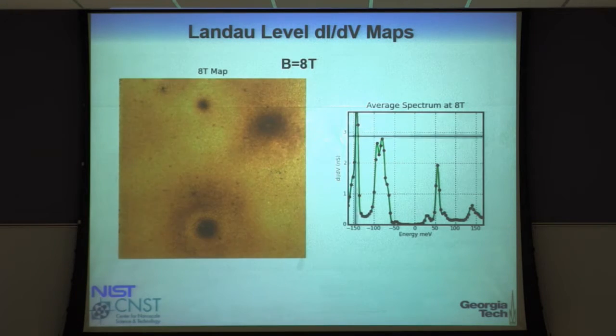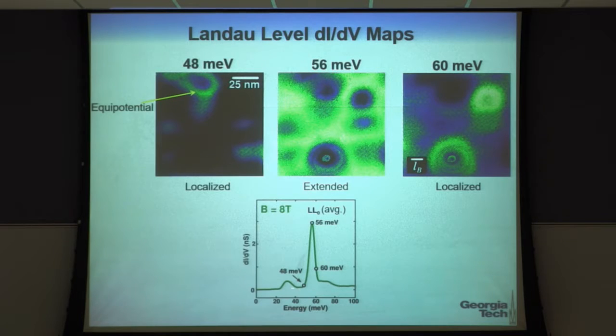What you're seeing is, again, the distribution of Landau levels on the surface. And if I look at an energy that's below the mean of the Landau level, I see a ring like this. And what's going on is that I get a cyclotron orbit that's going around like this. It's very, very small, and it's circling on an equipotential, okay? And if I go above the Landau level, I get things that circle equipotentials that are rises in the surface. If I stick right on top of the Landau level mean energy, I see this distributed all across the sample. In fact, it is these states that destroy the quantum Hall dissipationless state and quantized Hall conductance. And they destroy it because through this state, I can couple one edge to another.